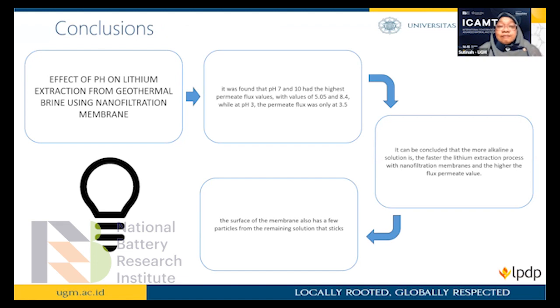In conclusion, regarding the effect of pH on lithium extraction from geothermal brine using a nanofiltration membrane: first, it was found that pH 7 and 10 have the highest flux values, at 5.05 and 8.4, while at pH 3 the flux is only 3.5. It can be concluded that the more alkaline the solution, the faster the lithium extraction process with the nanofiltration membrane and the higher the permeate flux value. And the surface area of the membrane also has a particle from the remaining solution.